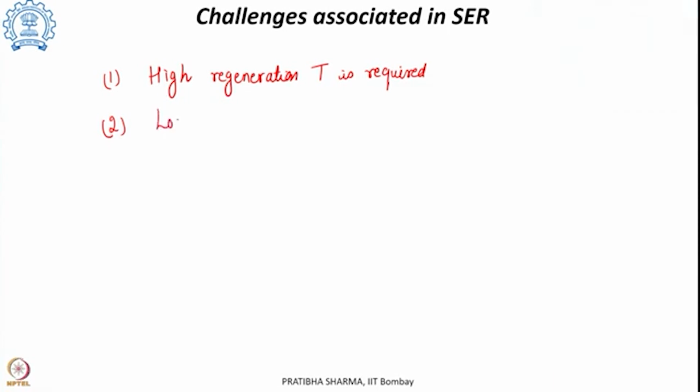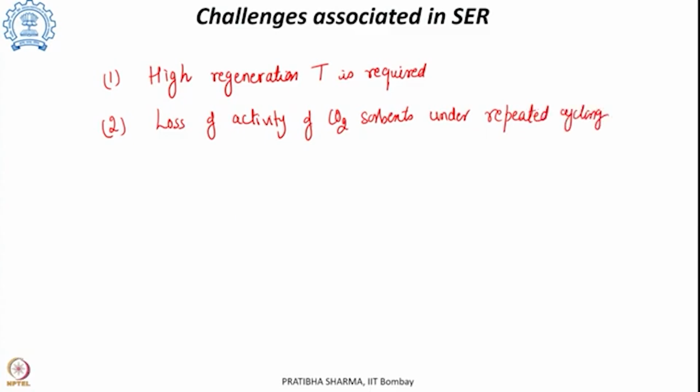At the same time, the sorbents are found to lose their activity when they undergo repeated cycling. The sorbents break, they undergo sintering, they undergo structural changes and need to be replaced.